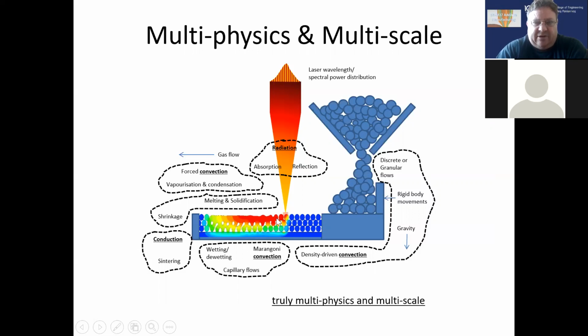During this interaction between the laser and the radiative source, we've got both vaporization and condensing happening within this gas flow, which carries away small plumes. We've got melting and solidification at the powder. So this part in the powder bed with the monosize powders is an actual simulation. So you can see the thermal contours underneath where the laser has traveled, going through the contact points of the powders, and you can see that there is effectively a conduction through the powder down onto the substrate. And you can see the melting and solidification, and at the same time you then get shrinkage.